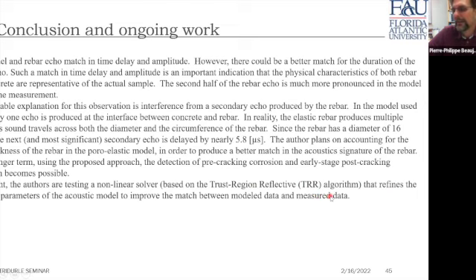And in addition to that, we are performing ongoing acoustic measurements with the new 3 samples that I showed in the previous pictures. A sample with very little corrosion sign, a sample with some amount of corrosion in the rebar, and a sample with severe corrosion. And these samples are undergoing acoustic measurement, and we are in the process of matching the measurements we made with what the poro-elastic acoustic model would predict. So this is the stage we're in.